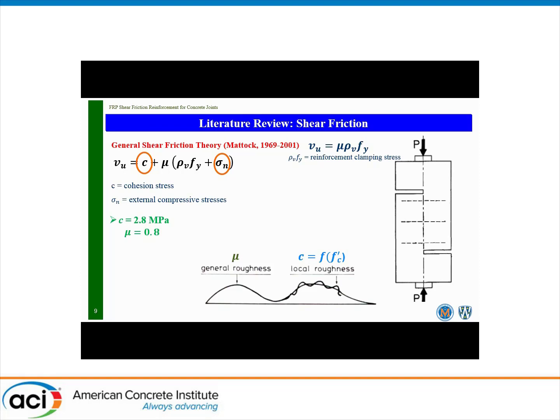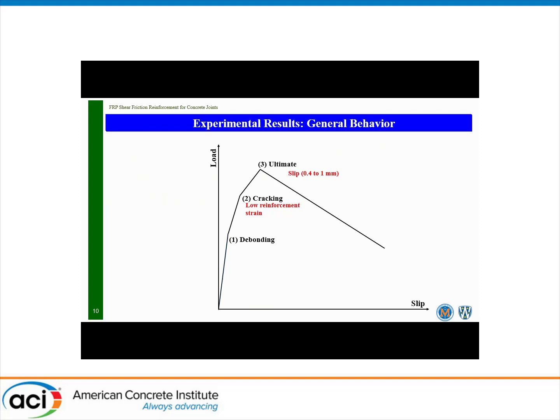The most famous way used to develop theories over the years is by simply carrying out tests on a very simple but famous push-off specimen, which was adopted in our approach. As per current literature about the general behavior of shear friction reinforcement using steel bars, the full load-slip behavior or stress-slip behavior can be categorized into multiple linear stages.